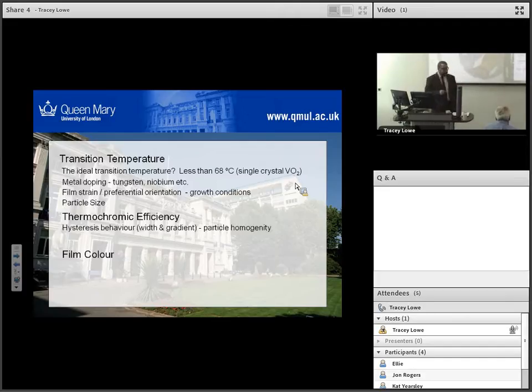The big problem then for metal doping comes with this thermochromic efficiency. Inevitably there's some hysteresis to this transition. One of the things that metal doping does is it changes the width and gradient. So actually this becomes a wider transition and a more gradual transition with metal doping. And actually that's not so good.